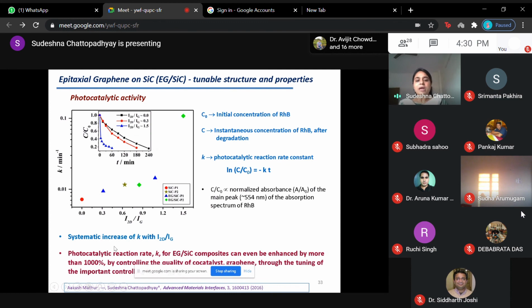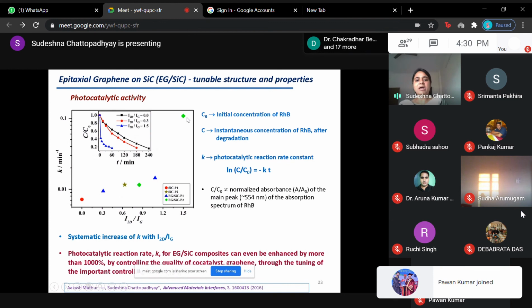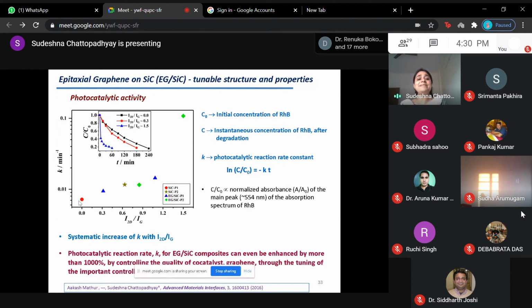If you compare graphitized silicon carbide with the normal silicon carbide, a few layers of good quality graphene can enhance the photocatalytic activity by 1000%. You can see this is more than 0.1 and as received was less than 0.01. If you just divide, you get around that percentage. So that shows how a few layers of graphene help to separate out the electron and hole and make it more active, making the photocatalytic activity much better and suitable for absorbing solar energy. That I will show in the next slide.